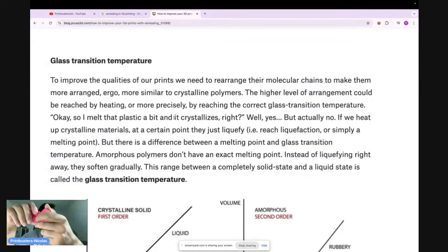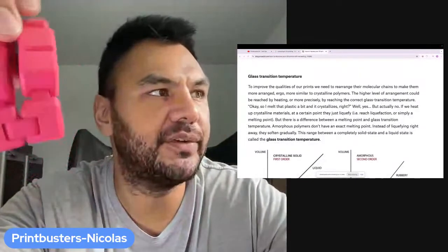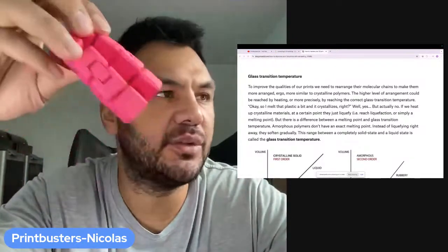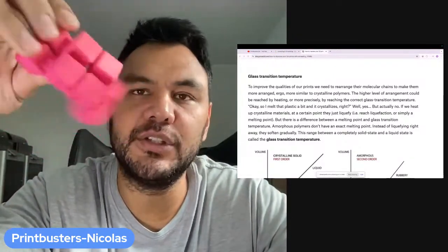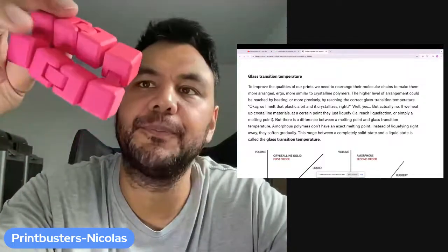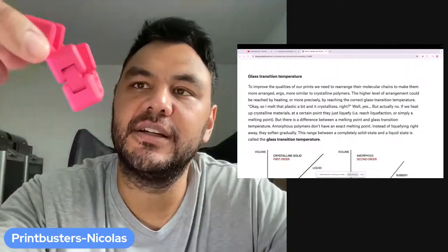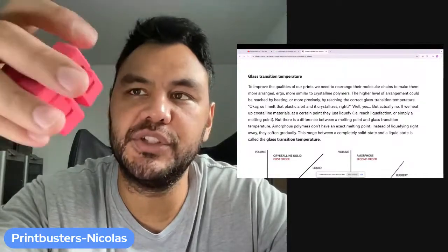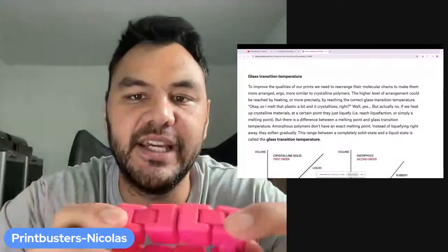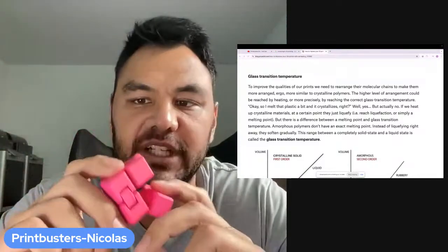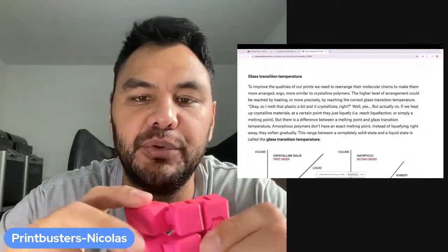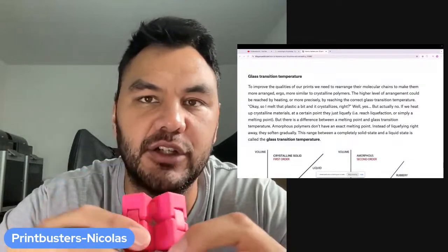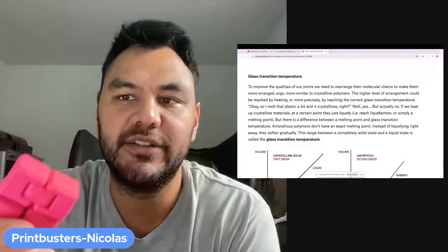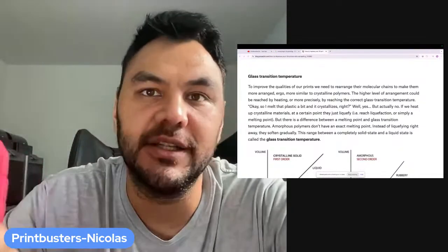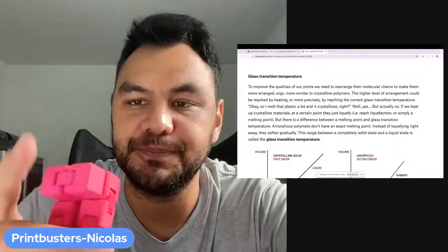If you print a part with regular PLA, right, that is not modified, in most cases it will be completely amorphous. Completely amorphous meaning that at 60 degrees C, the glass transition temperature, it will soften. Which means any type of load is going to deform the object, and so if you put it in the oven at 60 degrees, then it will basically collapse under its own weight, right? Because everything will soften. So any type of stress, even its own weight, will deform the part.